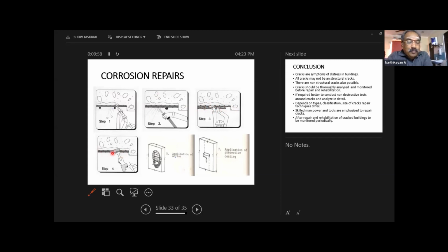And then apply anti-corrosive paint on the steel rebars. And also, as I said, apply a bonding coat, Nitobond, on the existing concrete. Then apply the fresh concrete, or micro concrete, or screed concrete on the reinforcement, and then finish with fine mortar and properly paint it. This step-by-step procedure should be followed. People do not use this method because it is a very skilled job. They simply call the masons and cover it with mortar or local concrete. Again, within a few months, it cracks again.